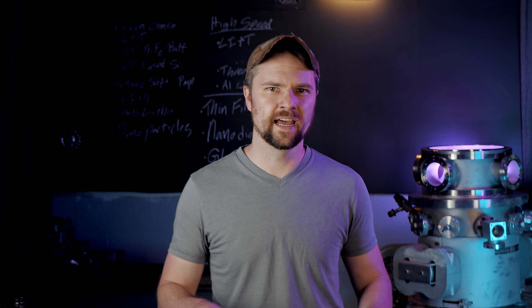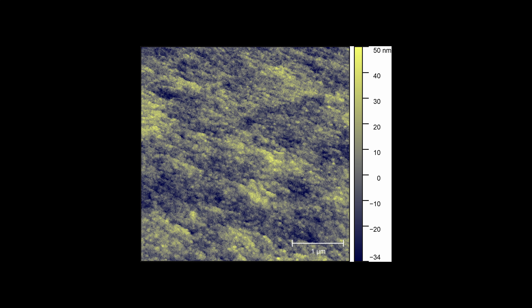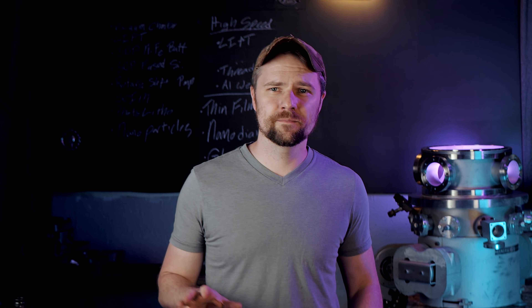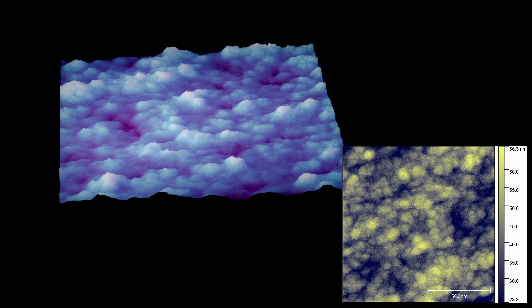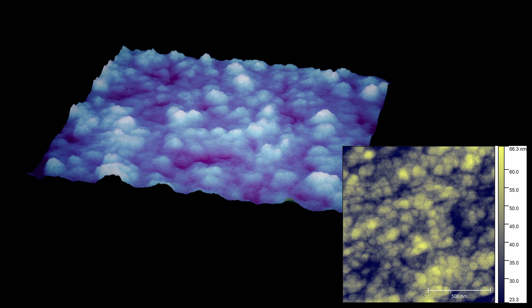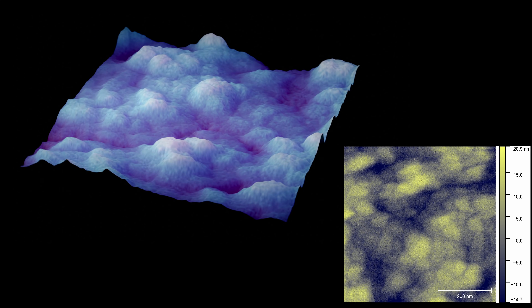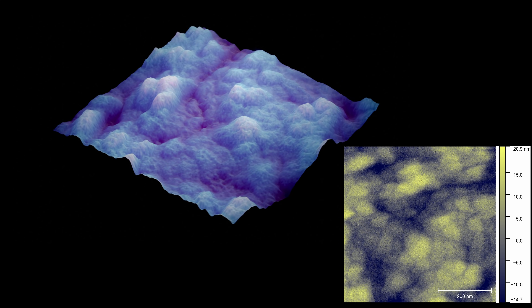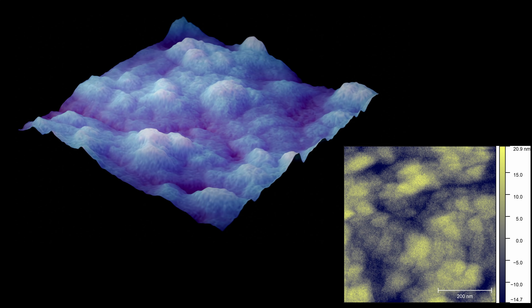Surface roughness came in at 15 to 30 nanometers depending on the sample. From there we can scan into a 4x4 micron view and start to resolve the individual nanoparticles a little bit better — this was already a really cool scan. But I wanted to see how close we could get, so I tried some 2x2 micron scans, and finally zoomed in all the way to a 500 by 500 nanometer scan, which is really quite a small volume. On average it seems that these particles are 50 to 150 nanometers depending on where you look and which particle you pick.